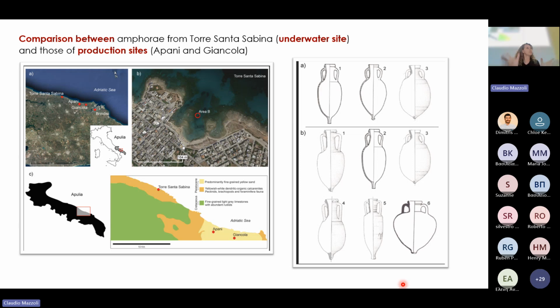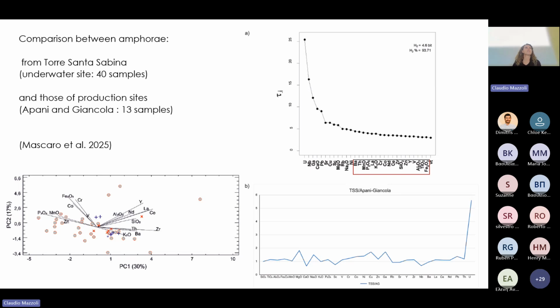So it's actually the same type of amphora, but one experienced the underwater post-depositional environment and the other is still present in the production site inland. So the thing that was done was to determine which were the elements much more variable in the system. And I know that this type of diagram may be difficult to read, but when the elements become stable along this line, which is asymptotic, you see this asymptotic behavior, while these elements here in the first part of the diagram are those characterized by a higher variability.